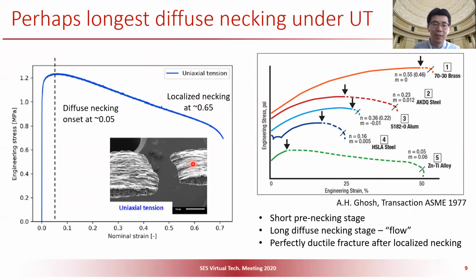And after that, we take the sample to see under SEM, and we find that here, this is the fracture plane. So lithium foil really fractures in a perfectly ductile fracture manner. That means localization happens, and the material is super soft and ductile.